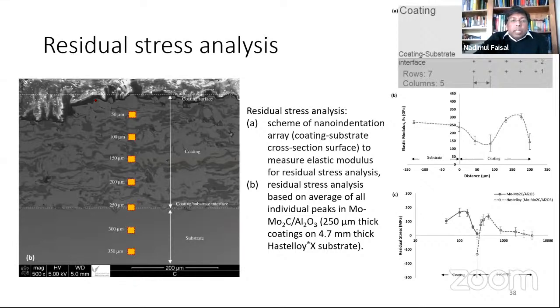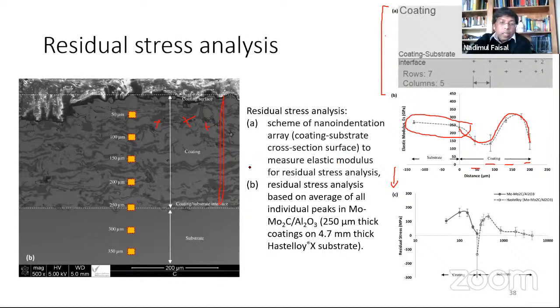Right, if you want to measure the stress, converting a strain into a stress, you have to measure the elastic modulus. In this case, what we did is take a cross section of the sample, and we did indentation testing on different points. So here is the scheme of those indentation points on the cross section. So either you take the elastic modulus value of the coating itself from some literature, or you measure it. If you want to do a proper measurement and use that value to convert a strain into a stress, like we have done here, you can see that for the coating part, elastic modulus is not constant. It varies from level to level where you are. However, for the substrate part, you can see it is very similar. So this is one way you can use it. Or if you want to simplify it, you can just pick one value to convert into a stress.